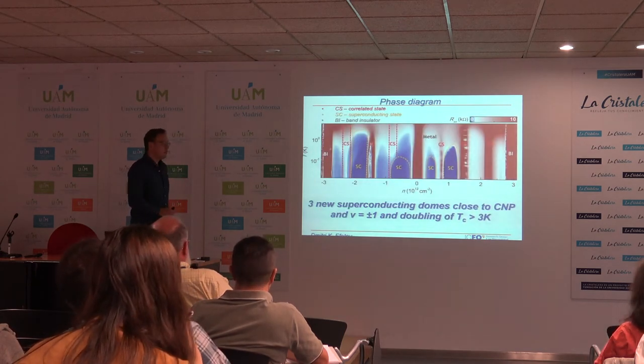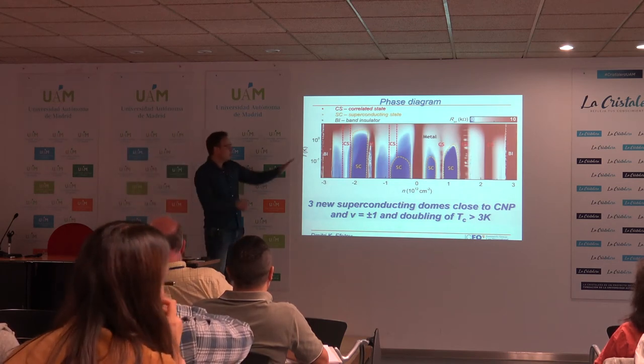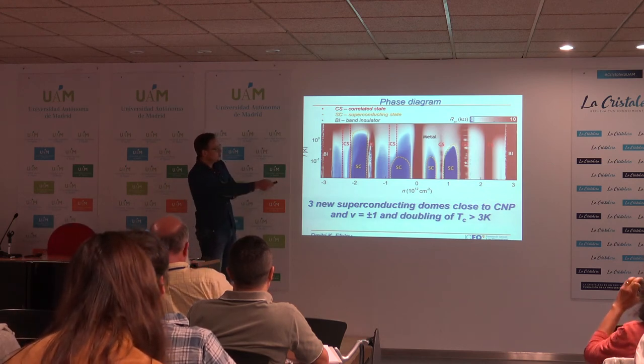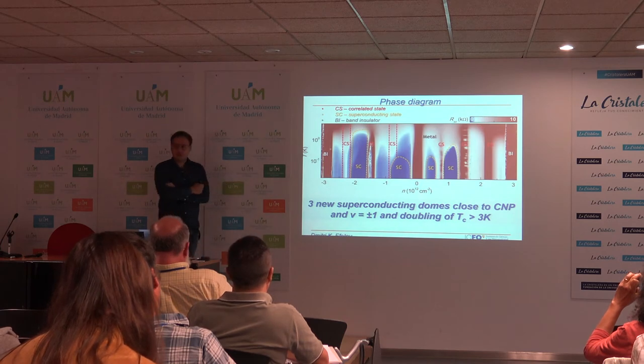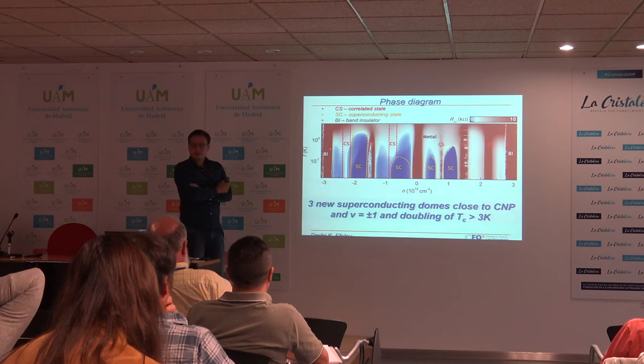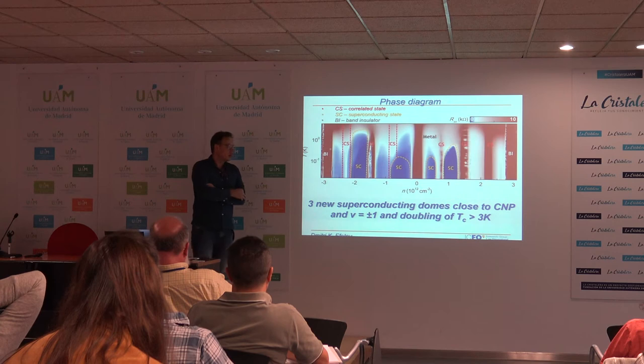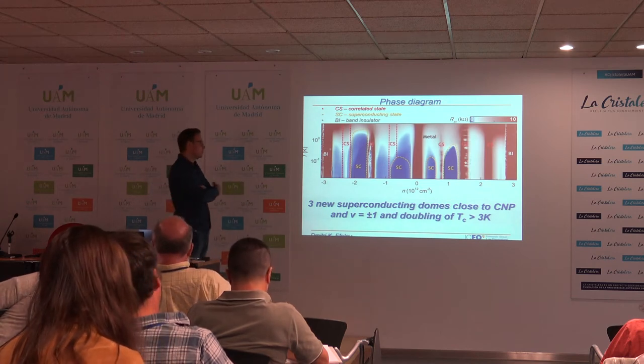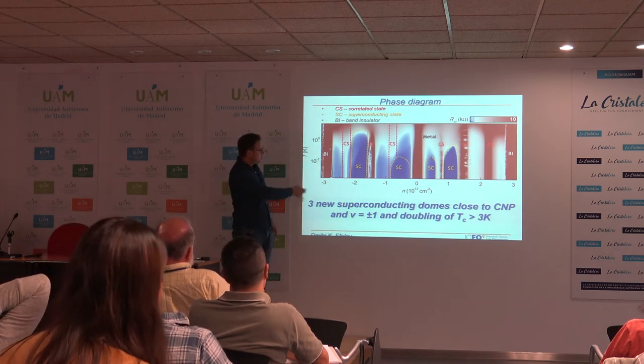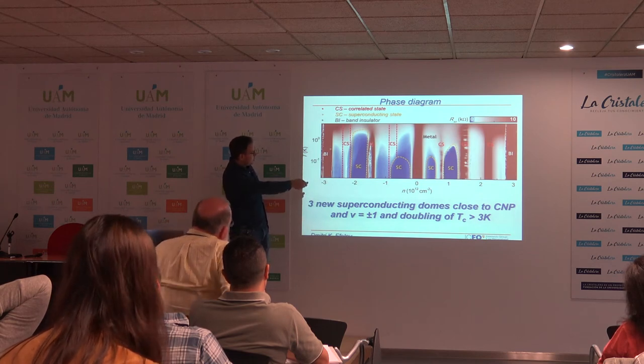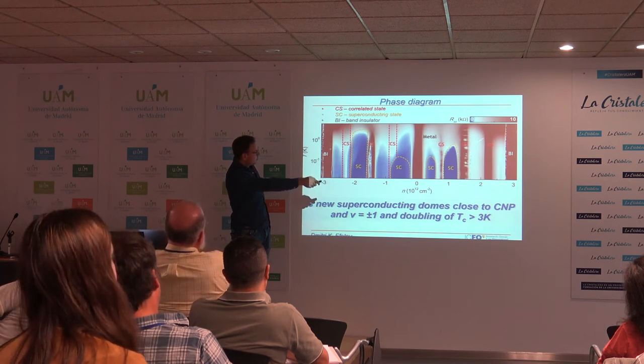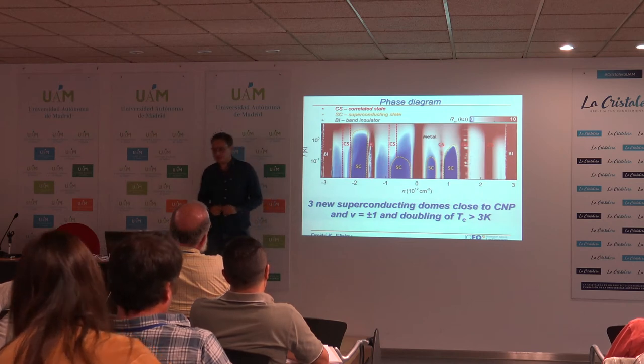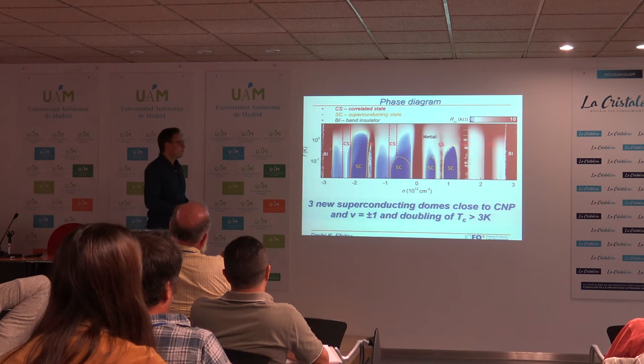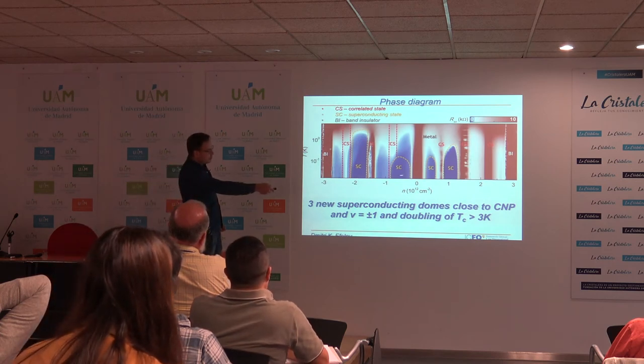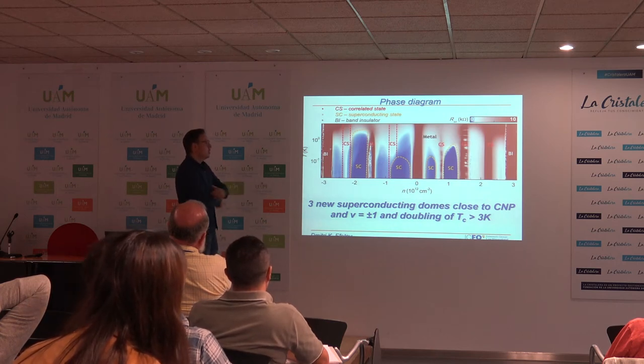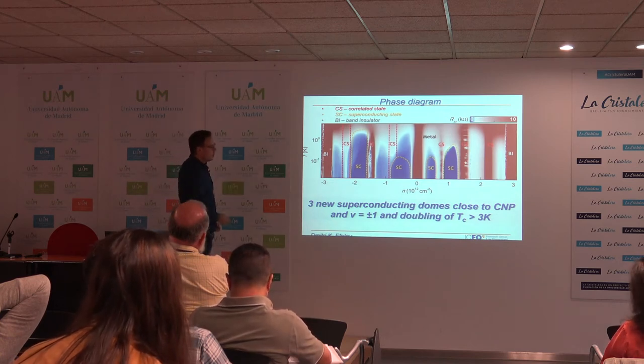And the evolved phase diagram is now the following, where, again, this is all plotted in the same color scales which Pablo was using. So basically what we're plotting here is resistance as a function of temperature and carrier density. Red regions correspond to highly resistive states, so these are the insulating phases, and the dark blue regions are the superconducting states, where resistance drops to zero. So you can see, again, here on the edges, the band insulators, in the center there's a charge neutrality point, and then here, these are all the correlated states at all the integer fillings, and in between almost all of the correlated insulating states, we see superconducting states. These three, for example, these two, which are close to charge neutrality, and this one here, which is close to the filling factor 2 here, these are the superconducting states, which are new.